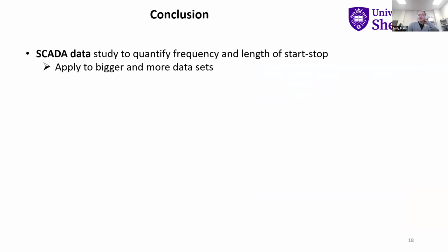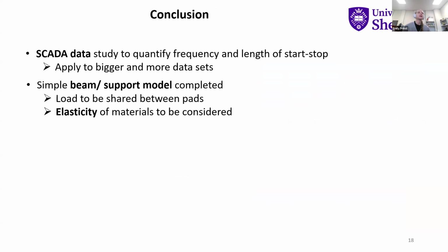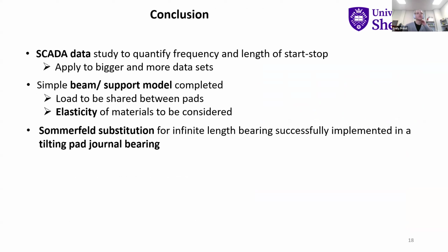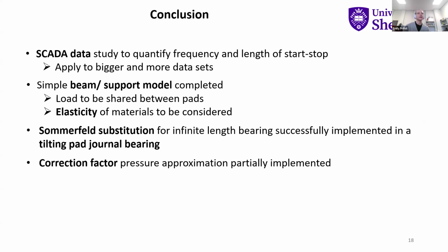So to conclude, we did a SCADA data study to quantify the frequency and length of start-stops, but we want to apply that to bigger and more data sets to verify the results we've got. We've done a simple beam support model, but we need to share the load better between pads, and we also need to consider the elasticity of the materials. We conducted a Sommerfeld substitution for an infinitely long bearing and successfully implemented that for a tilting pad journal bearing. We applied the correction factor using that Sommerfeld substitution to find the pressure approximation, and we've partially implemented that and